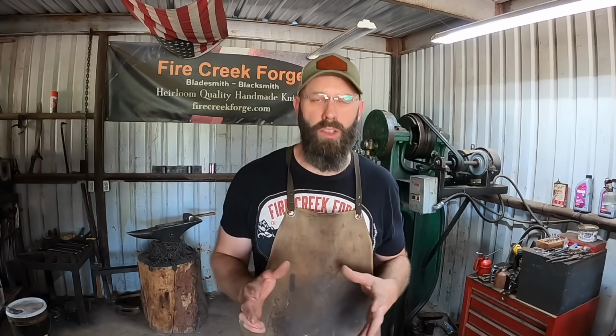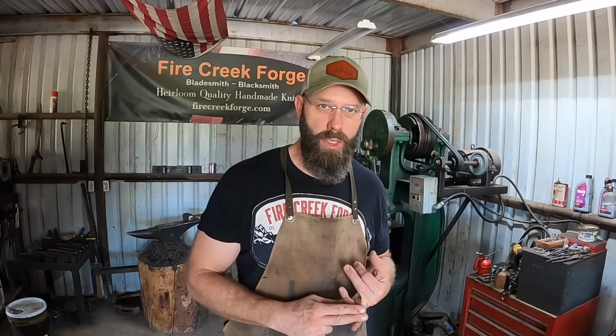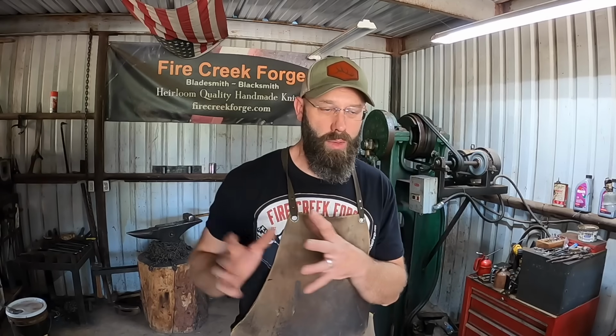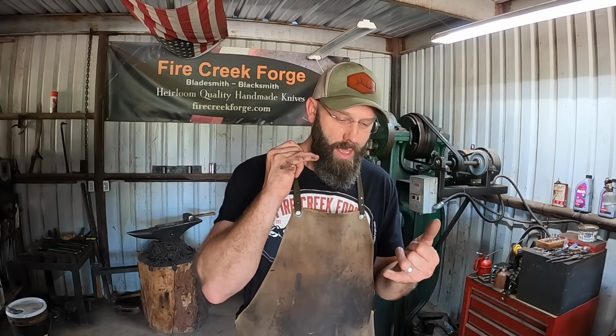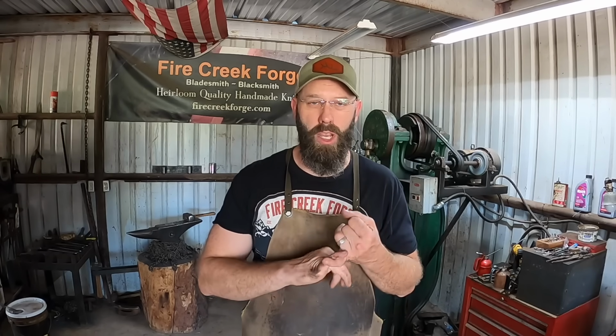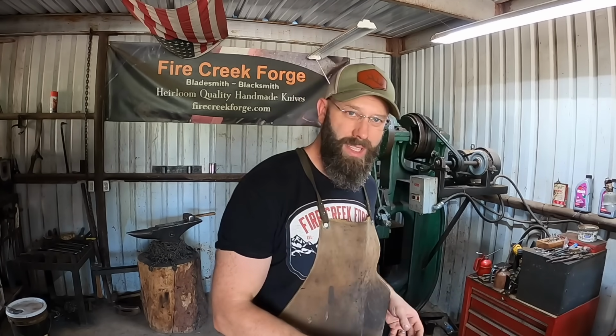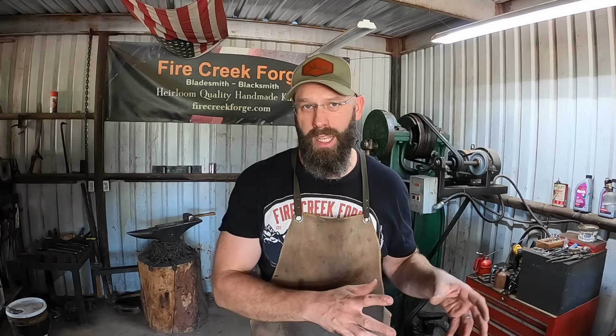And in this case, it has a lot to do with the fact that it's a high alloy, high carbon steel. Higher austenitizing temperature, more carbon into solution, more of that chromium is combined with the carbon to create carbides. Less of it's available to make the steel more stainless, and also less tough, more carbides, less toughness. But then you can bring that down a little bit, still have a good amount of carbides for abrasion resistance, but leave enough of that chromium in solution so it's more stainless.